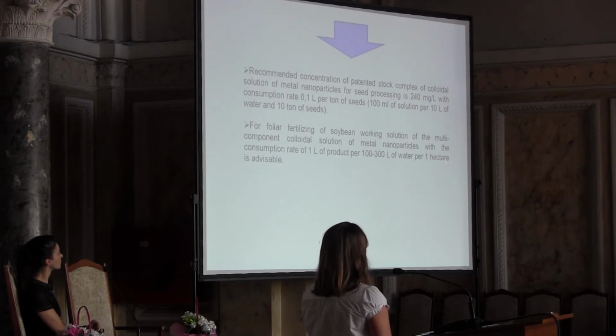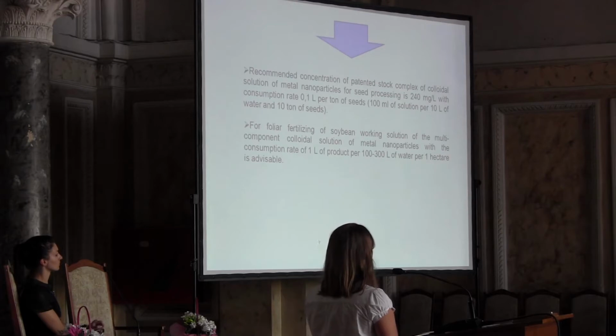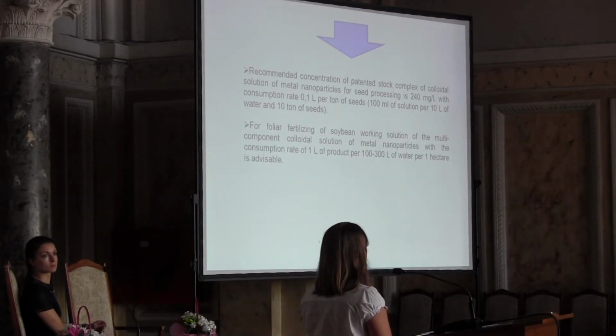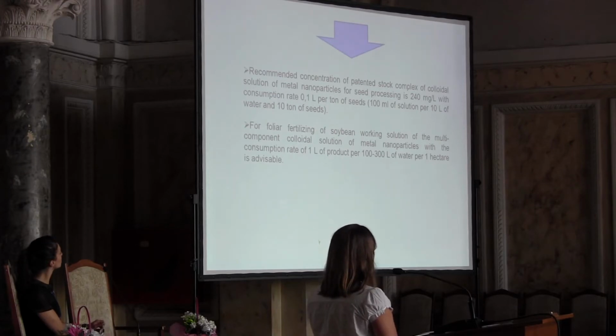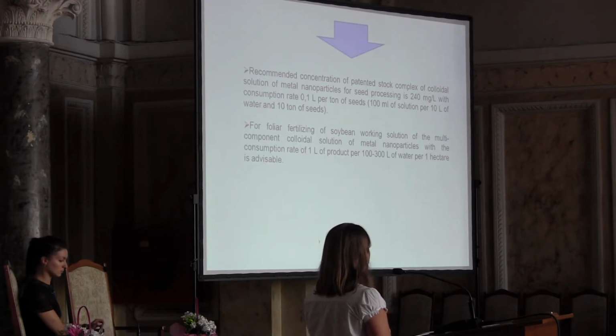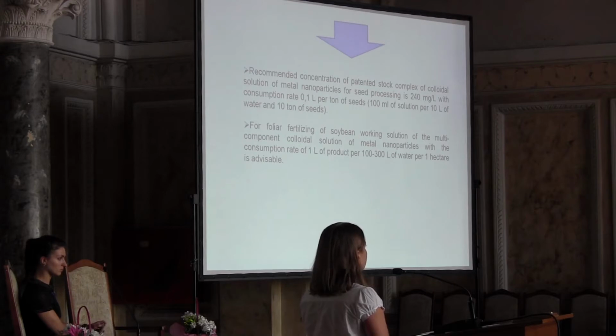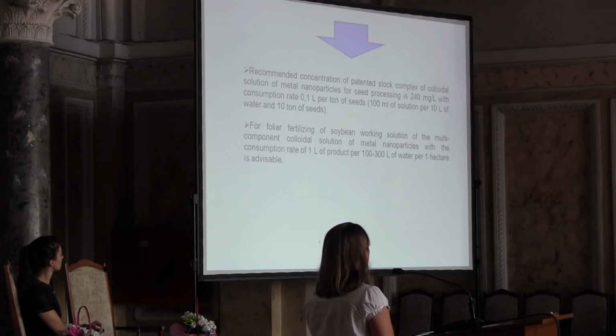So we could recommend the concentration of colloidal solution of metal nanoparticles for seed processing of 240 milligrams per liter with a consumption rate of 0.1 liters per ton of seeds, and the same concentration was favorable for increasing soybean yield by foliar fertilizing of soybean.